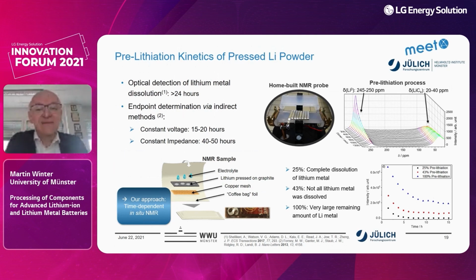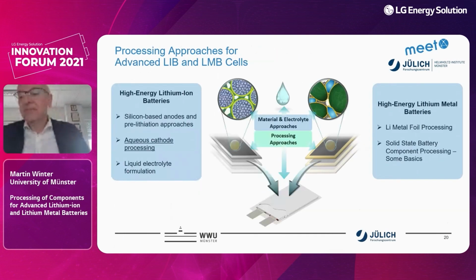And if we take exactly the capacity of the electrode, 100% lithium metal, then we see that some lithium metal remains. So you cannot compensate, obviously, for all the capacity that is needed to lithiate the cathode. So there's always some lithium metal remaining if you take 100% of the capacity of the anode. So this is something which has to be regarded. What we learn here is after about 5 hours, pre-lithiation is finished. So 5 hours is quite some time. This was the pre-lithiation topic.